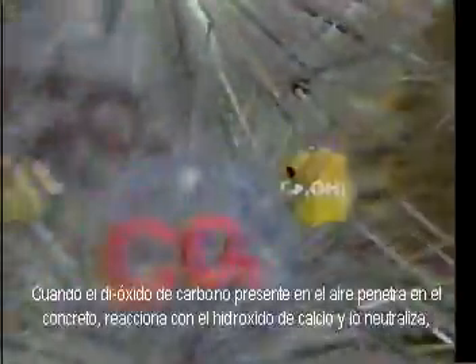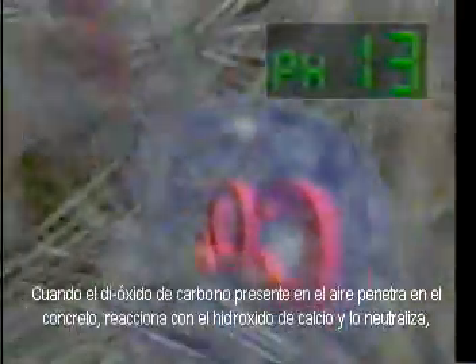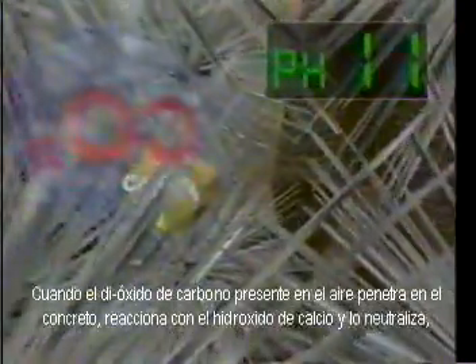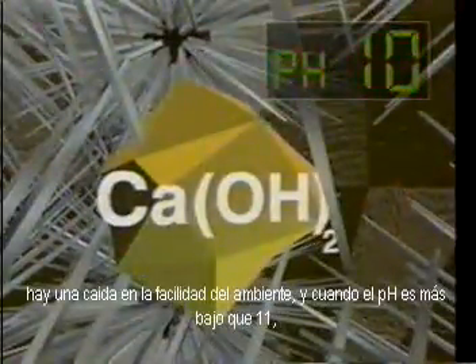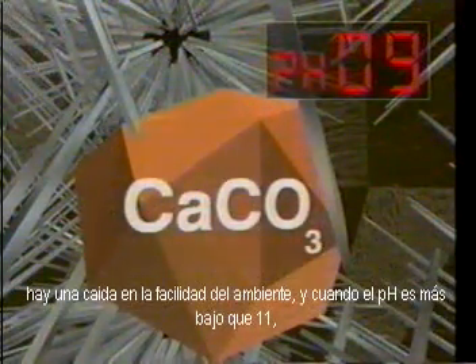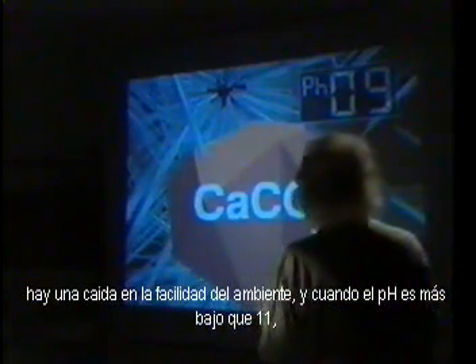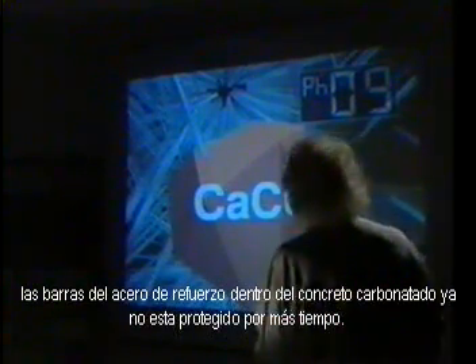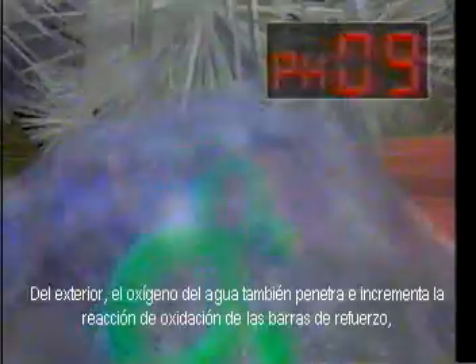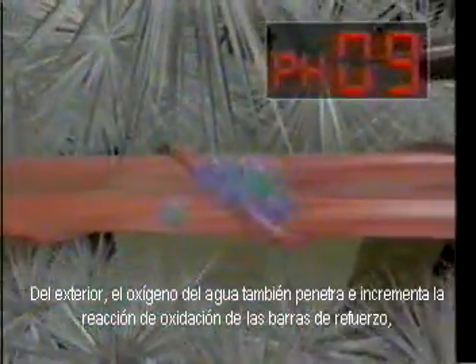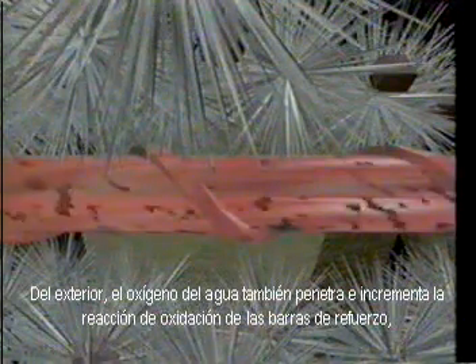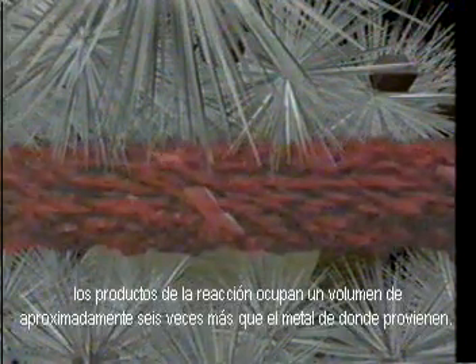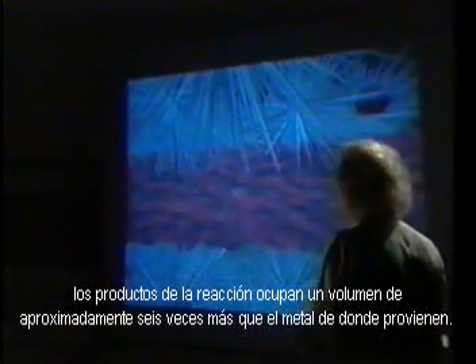When the carbon dioxide present in the air penetrates into the concrete, it reacts with calcium hydroxide and neutralizes it. There is a lowering of the basicity of the environment. And with a pH below 11, the steel reinforcing bars inside the carbonated concrete are no longer protected. From the outside, water and oxygen also penetrate, thus increasing the rusting reaction of the reinforcing bars. The rust which forms occupies a volume of about 6 times more than the metal from which it originated, and so causes the cracking and expulsion of the concrete cover.